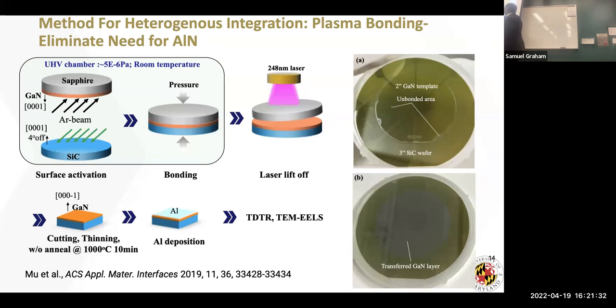The reason why we did the two like this, it was easier to get the gallium nitride templates in that size. Commercially, they're harder to find at the larger scales. So we can bond these together, and you can see this can be done at wafer scale. And then what we've done is another cut to only leave behind a very thin layer of gallium nitride, so we can do thermal measurements by time domain thermal reflectance through this in order to measure how resistive that interface is. Remember the picture I showed you, we had aluminum nitride, we get rid of it, there's no aluminum nitride here.